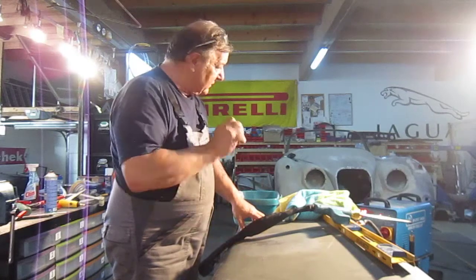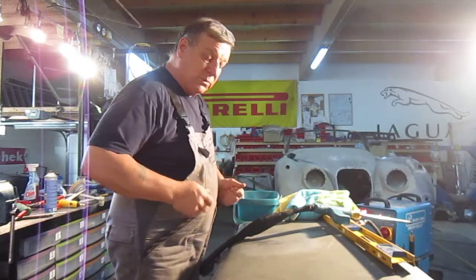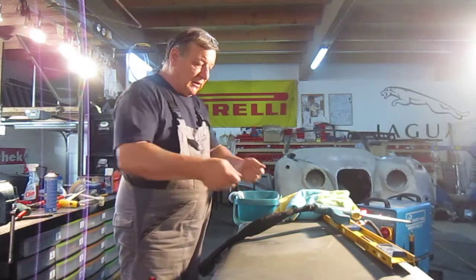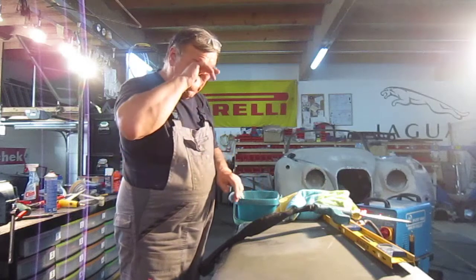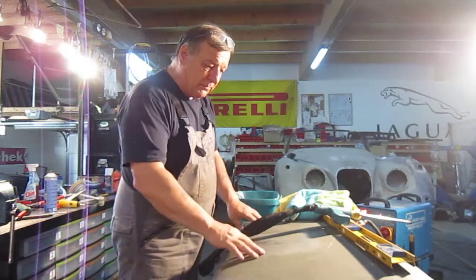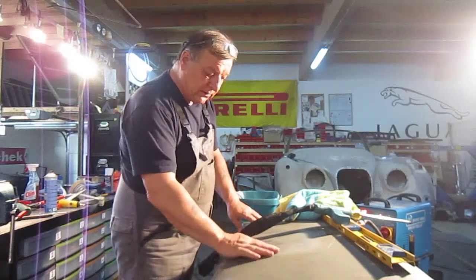We nipped it just a little bit too tightly. And when we rolled it, the English wheel doesn't need to be too tight — you don't put a lot of pressure on it. As you wheel it, obviously you're flattening the metal out. There was a very bad crease in here which we got out, but I think I over-wheeled it. And what's happened is it created a little bit of a lump there.